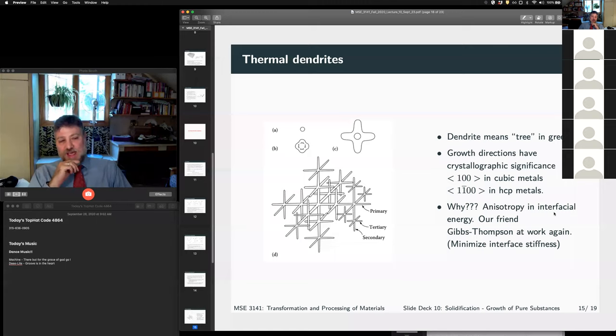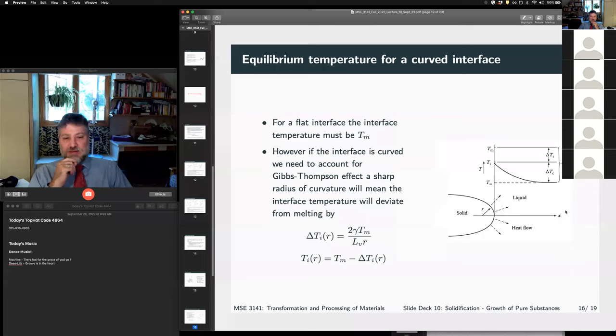And so why does this happen? Because of the anisotropy in interfacial energy, right? This is Gibbs-Thompson at work, right? These are the directions that minimize the interfacial stiffness, so it's easiest to make a sharp radius along these directions. So the little bit of difference between interfacial energy along the different crystallographic directions magnified by a tight radius in the Gibbs-Thompson means that we're going to have preferential direction of these dendrite arms, right? So the dendrite arm spacing is primarily in cubic metals going to be at 90 degrees to each other, right? Which is good because it happens to be a really good space filling type direction, okay?